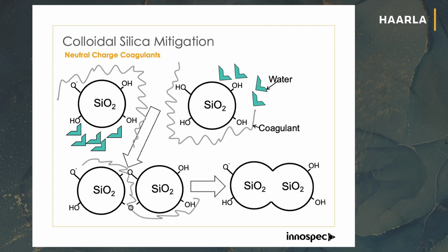How is that actually done? There are two different types of coagulants normally used. There's the one without charge, referred to as a neutral product, and then there's the one with charge, which is normally a cationic product. The silica particle associates with the water. The water then gives you a crystal structure, and it keeps the particles apart. What the coagulants do is interfere with that water absorption and displace the water, stopping the water going on, which then allows the silica particles to come together, and then the silica particle grows.